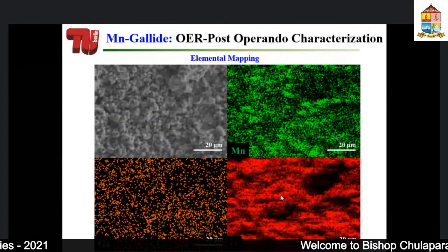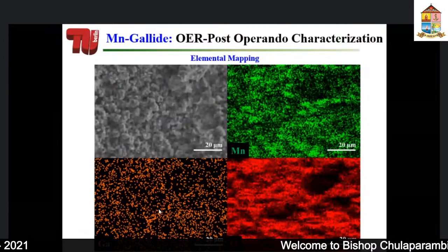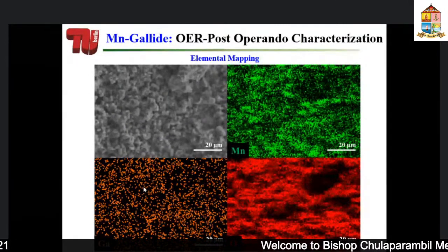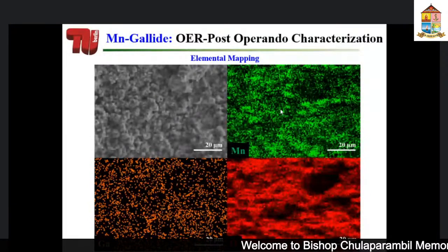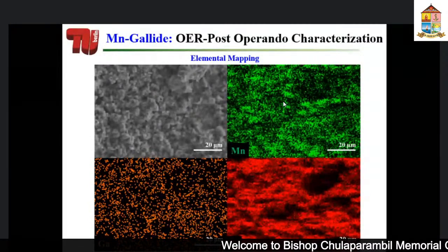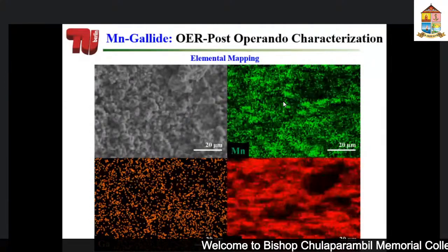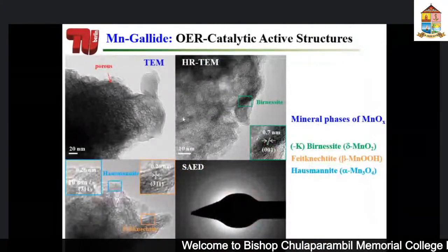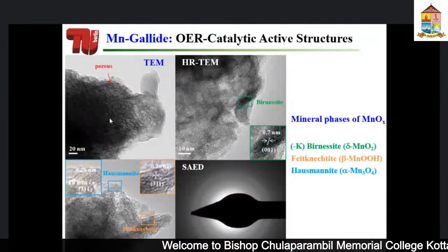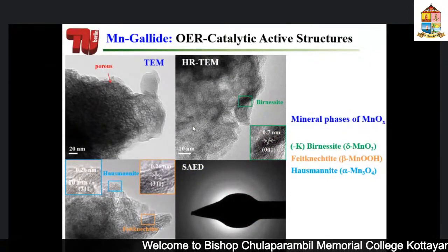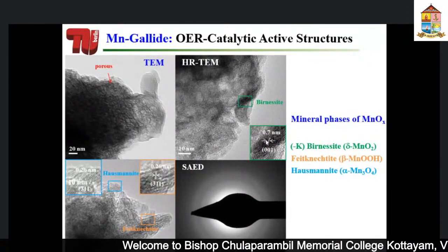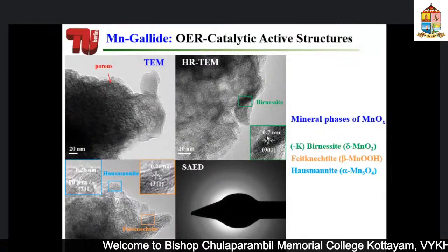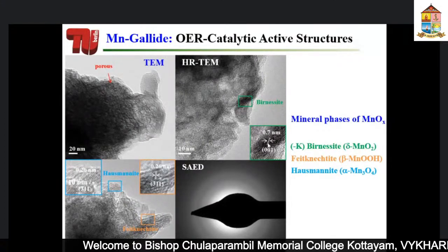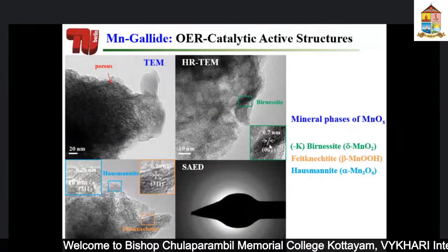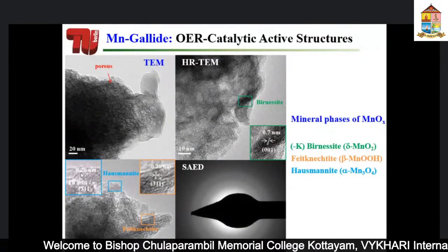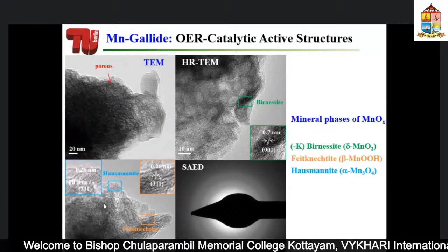Again, we looked into the structure, what happens after, and we saw that gallium is completely leaching out of the structure, and what you form is more or less manganese oxides. This can also be shown in TEM, or transmission electron microscopy. These are the fringes which you could see from the high resolution spectra. This means that these are the lattice fringes, which can be directly correlated to the reflections of your XRD pattern.